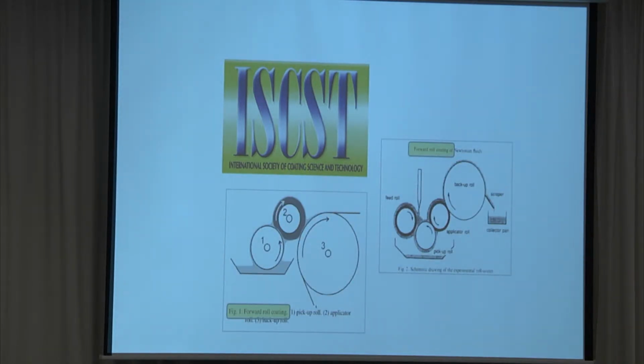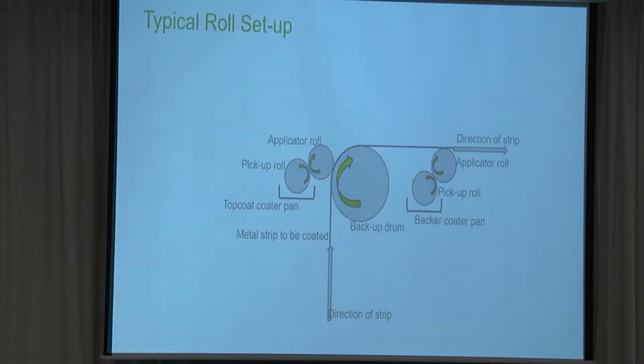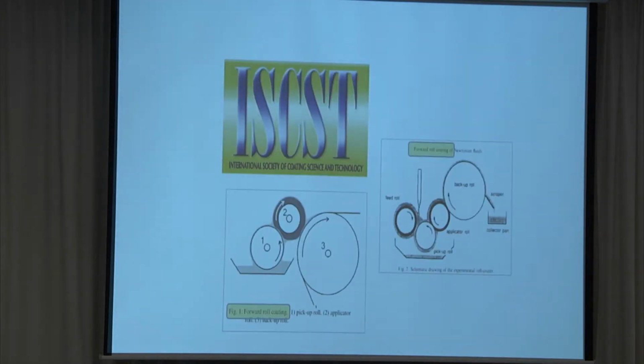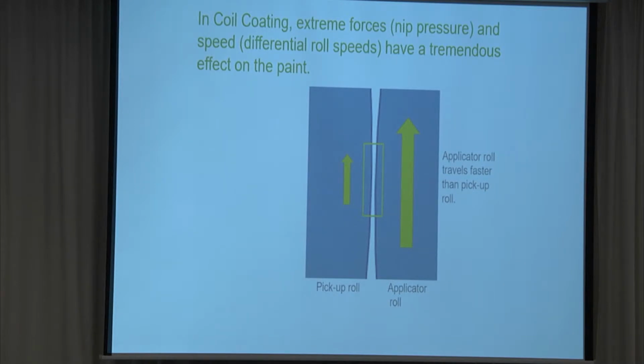But what I grew up calling reverse roll coating, because the applicator is going in this direction and the web is going in this direction, these guys call forward roll coating. And I had a long talk with them, and their point was this process right here, where the rubber roll puts the paint onto the web, that's a wiping process, that's a low shear process. All the shear is between the pickup roll and the applicator roll. So, it's really the differential in speed that's occurring along with the pressure and the durometer of the applicator roll that makes a difference.